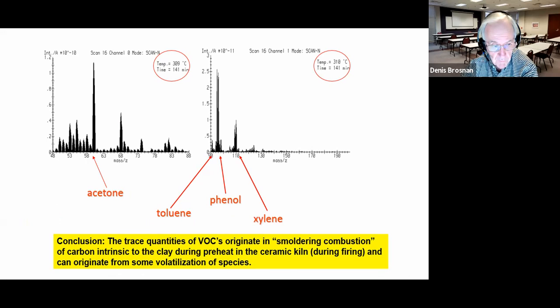Now, a lot of you will recognize that those are components of solvents that are being emitted in the heating situation, maybe in very small quantities, because this was an extremely sensitive instrument that was being used. Mass spectroscopy is typically not used in stack testing, but these are things that are being emitted in the molecular weight range for acetone, toluene, phenol, and xylene. So nevertheless, this is why regulators can find fragments of molecules floating around in your kiln atmosphere that they detect as acetone. Is acetone actually there? I can't tell you, but something with that molecular weight is there.